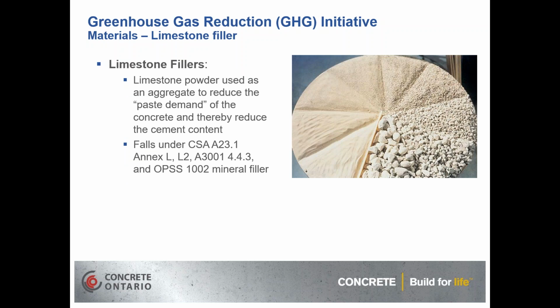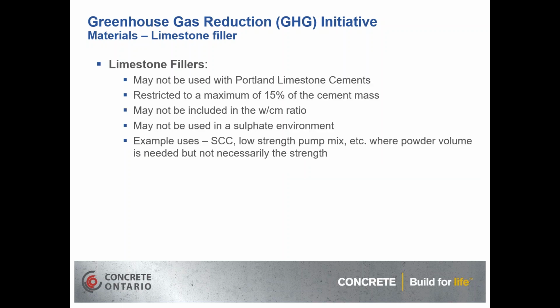Limestone fillers. These are limestone powders used as an aggregate to reduce the paste demand of the concrete and thereby reduce the cement content. And these fall under CSA A23.1 Annexes L and L2. It's mentioned in A3001 4.4.3 and OPSS 1002 specification on mineral filler. Now, some considerations with the limestone fillers. They may not be used with the Portland limestone cements. Again, it's only one or the other.